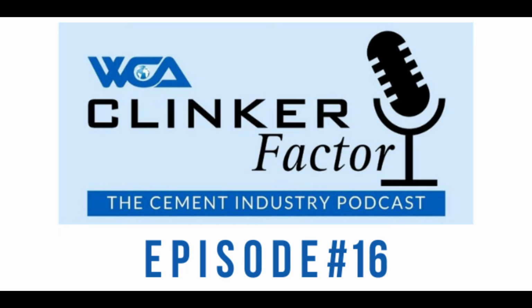So can you explain how Carbon8 Systems is using that process and what products or services you're offering to the cement industry? Well, having worked principally with cement and thinking about carbonating cement, we realised that there are a lot of industrial residues which contain the same magnesium, but more particularly calcium compounds. So principally lime, but also calcium silicates, which would react with the CO2. So you're looking at things like steel slags, cement residues, both bypass dust and kiln dust, and then residues from energy from waste, both the bottom ash and the fly ash or the air pollution control residues. And then things like paper ash or biomass ash can be variably reactive with CO2.